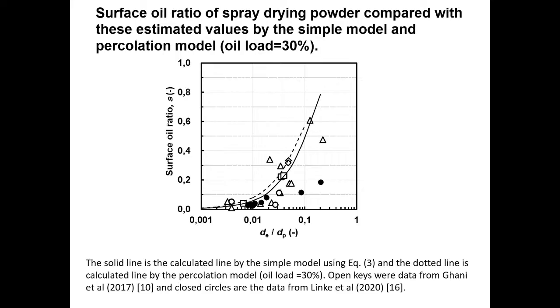This is the surface oil ratio of spray dried powder compared with the values estimated by the simple model and the percolation model. This is DE, the average oil droplet size, divided by DP, the average powder size. Surface oil ratio means the ratio of not encapsulated oil to total oil in the powder. Usually for industrial products, this ratio is below 0.01.